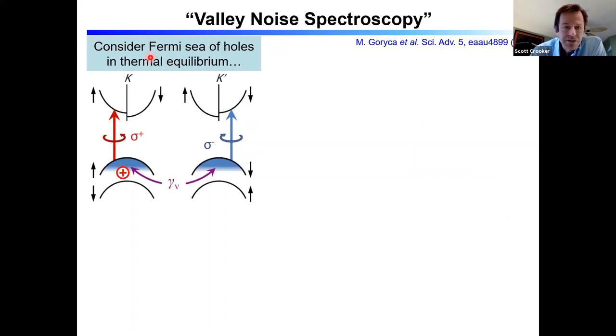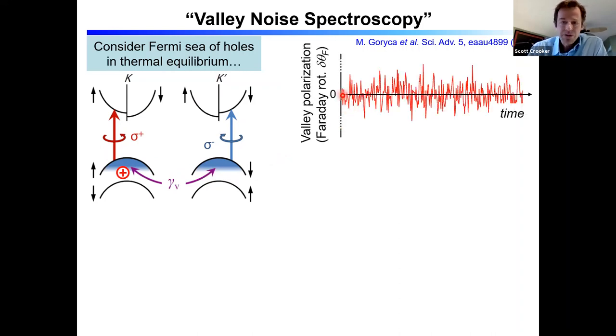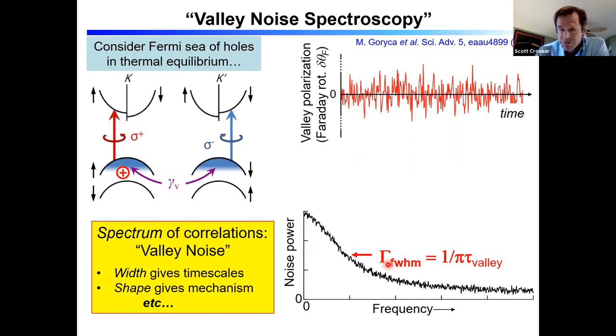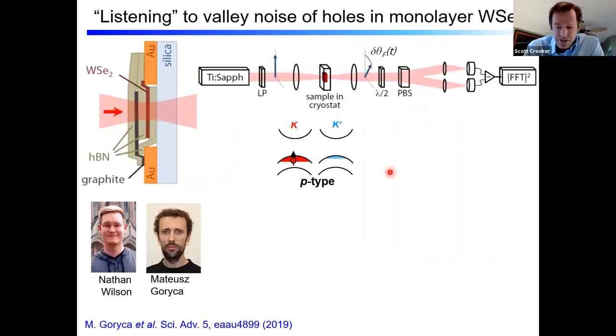So if you consider just a Fermi sea of, in this case, let's just talk about holes, a monolayer doped with holes in thermal equilibrium. Again, this is meant to represent the thermal fluctuations that occur as holes scatter between K and K prime. Maybe we can measure that using our optical approach. And if we can measure these noise signals, then we could back out the noise spectrum, and the width of that spectrum would tell us what the characteristic correlation or relaxation time is, exactly in the same way that we did for atoms or for conventional semiconductors. So that was the experiment.